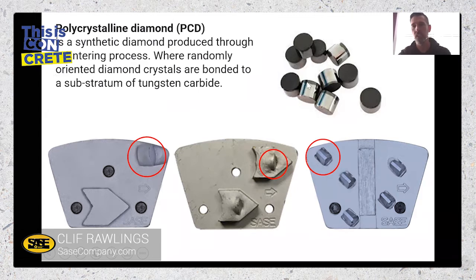So if you look closely in this picture, you'll see just that top sliver, if you want to call that a 16th or an 1/8 of an inch, maybe even. That 16th of an inch is basically the PCD. That's the polycrystalline diamond that's grown on top of this cylinder, which is tungsten carbide, okay? So that's how life starts as PCD. They take these PCDs and you can either put them as a whole PCD. In this scenario, you can see right here, where it's a full PCD.